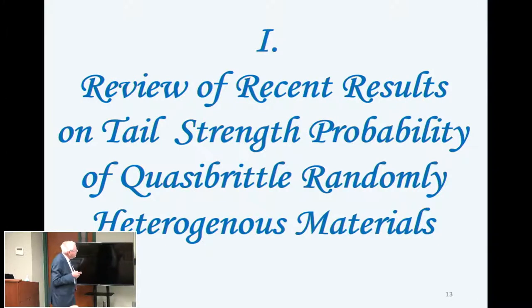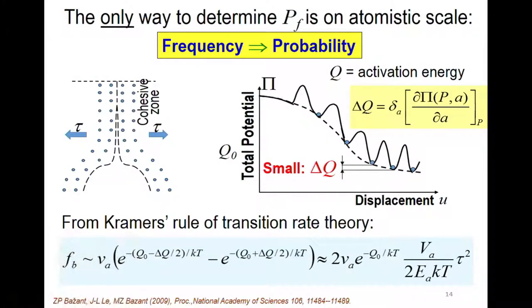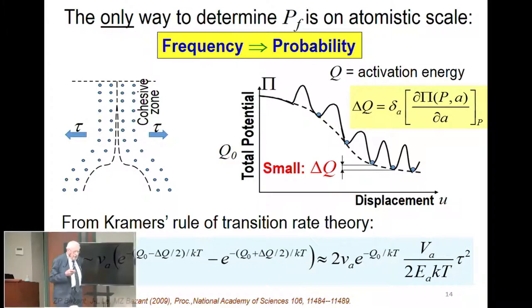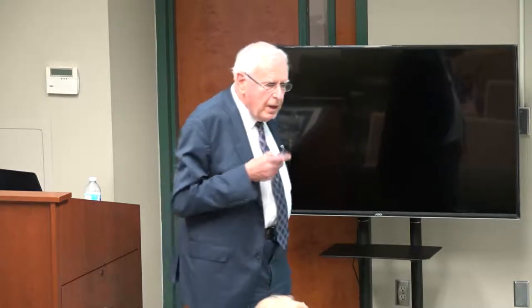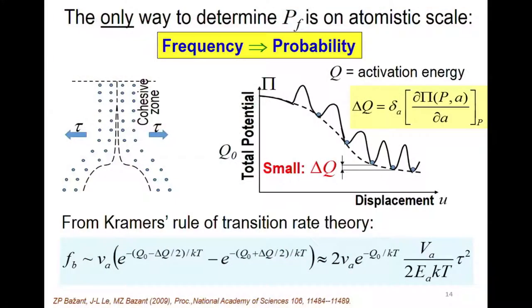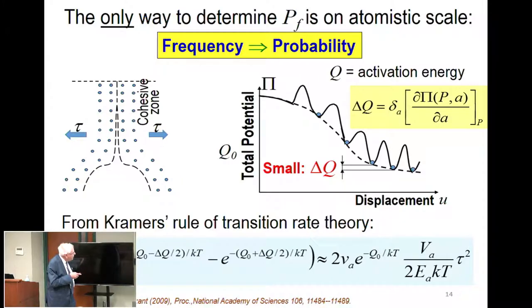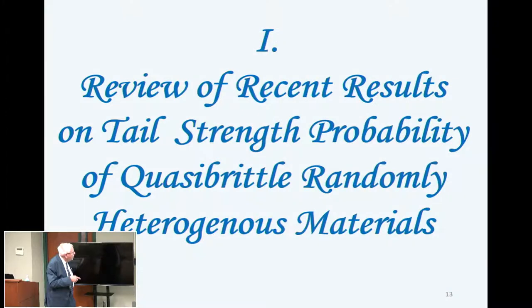So let me first review briefly some results obtained over the last about 12 years. How to approach it? There is a theory of Freudenthal, who derived the distribution by considering the statistics of critical size flaws, maximum flaws. It's a correct theory, but it really relates one scale of flaws to another, and derives one set of properties from another set of assumptions. The only way the probability is known exactly is at the atomistic scale, and the reason is that at the atomistic scale, the frequency of the breakage of bonds is exactly equal to the probability of the breakage of bonds.